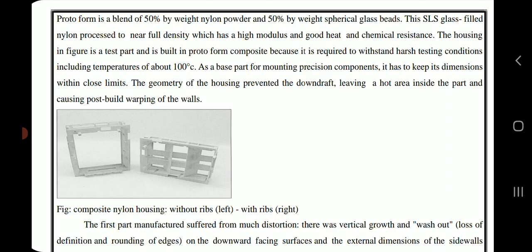The housing in the figure is a test part and is built in Protoform composite because it is required to withstand harsh testing conditions, including temperatures of about 100 degrees Celsius. As a base part for mounting precision components, it has to keep its dimensions within close limits. The geometry of the housing prevented the downdraft, leaving a hot area inside the part and causing a post-build warping of the walls.